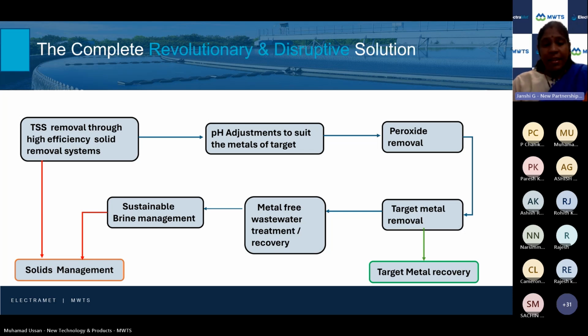And this entire technology can remove peroxide, but that is not the intended goal, because we are focusing on taking off the valuable metals. So we have a more economic solution for the peroxide removal so that it doesn't interfere with the core technology. But the difference is peroxide does not have a detrimental effect as it does on ion exchange technology. So we can take care of the peroxide well before the system. But even if peroxide is there, it is not going to degrade the system, but it is making it less efficient. So we thought we should be knocking off peroxide even before getting into the target metal removal.